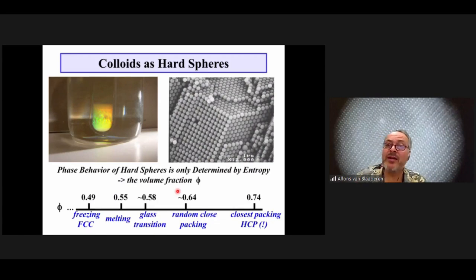If we have particles with hard interactions, the free energies of the close-packed crystals are very close together, but they form face-centered cubic crystals when we reach a volume fraction of 50 volume%, and then with the first order phase transition, you get crystals with a volume fraction of 55%. The free energy of the other close-packed crystals, like hexagonally close-packed, is very close by, but if you give the system enough time, they will form FCC crystals.